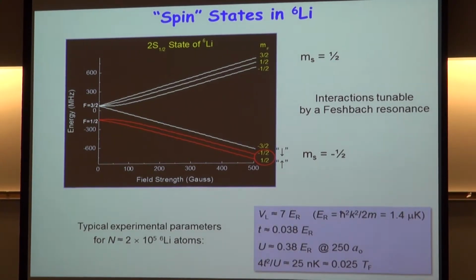These are some of the parameters that are relevant in our experiment. We have a few 100,000 atoms. Lattice depths are about 7 recoils. For lithium, a recoil is about 1.4 microkelvin, to set your scale. The hopping is something like 0.04 of the recoil. U is about a factor of 10 bigger than that, at a scattering length of about 250 Bohr. And the superexchange energy scale is a few percent of the Fermi energy. So that's the target.